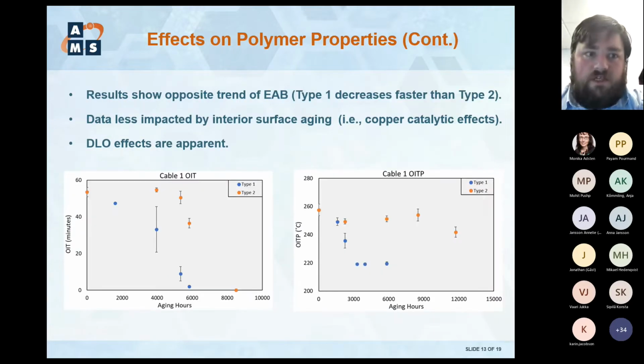However, in oxidation induction measurements like OIT and OITP, we did see the expected DLO effects. We saw that the type 2s were actually aging slower. The OIT, OITP values were aging at a slower rate than the type 1s, which is what we would expect to see.